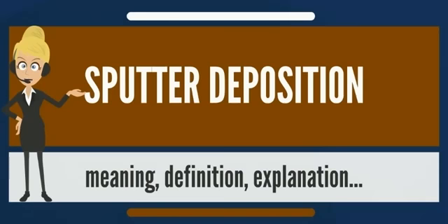Sputtered atoms ejected from the target have a wide energy distribution, typically up to tens of eV (100,000 K). The sputtered ions, typically only a small fraction of the ejected particles are ionized, on the order of 1%, can ballistically fly from the target in straight lines and impact energetically on the substrates or vacuum chamber, causing resputtering.